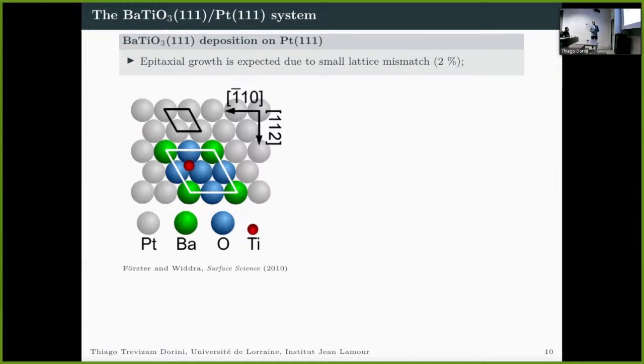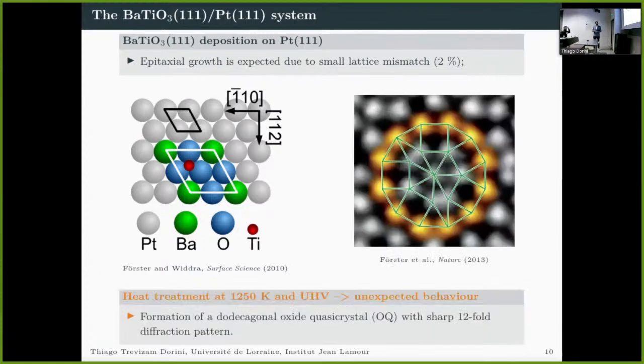In this work, Förster and Widdra were studying the surface properties of this phase when supported on a platinum 111 system. They used platinum specifically because it has a very small lattice mismatch with the 111 orientation of barium titanate. And to everyone's surprise, when you heat treat this sample at 1250 Kelvin in ultra high vacuum, there was a very unexpected phenomenon: a complete change in the structure of this perovskite, and the discovery of the first oxide quasi-crystal, which is a 2D material.